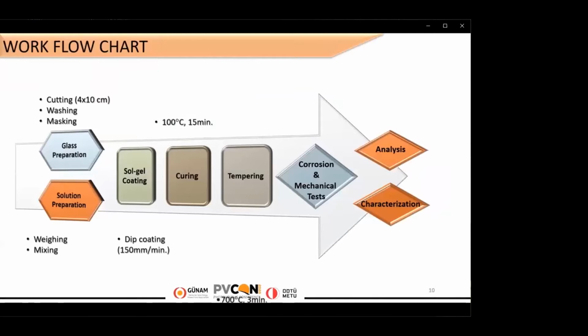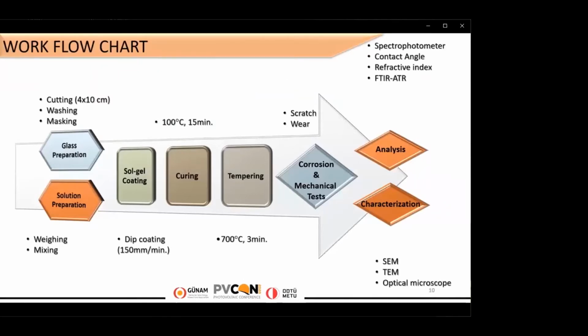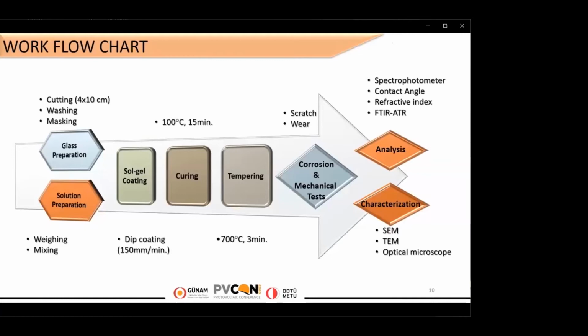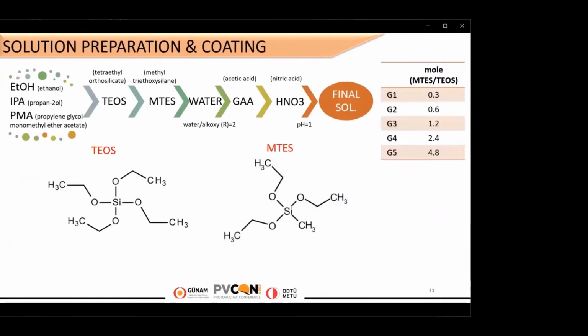First, glass substrates and solutions were prepared. Since we used dip coating method, one side of glasses was masked. After coating, coated glasses were cured at 100 degrees Celsius and tempered at 700 degrees Celsius for 3 minutes. In order to obtain optimum conditions, we studied all parameters such as withdrawal rate, temperature, and time, etc. Also, we did many tests, analyses, and used characterization techniques that you can see at the end of the flow chart to investigate details. Here is the solution preparation and coating steps.